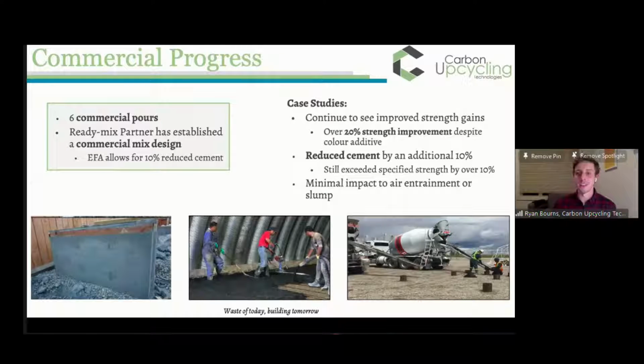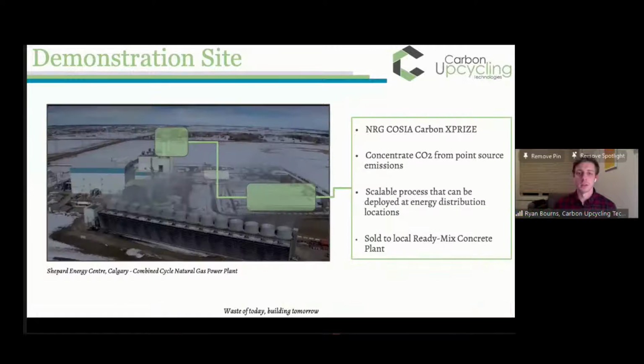As Matthew mentioned, there's a very thin margin that you can work within, and 40% is way above that. So what we really want to show is that because of that strength improvement, we can really reduce the cement that would be associated with it. This is something we're still working on and optimizing with our concrete partners. But what we've shown here is that we can keep all of the necessary considerations for concrete the same, whether it's air entrainment or workability, but with improved strength and reduced cement. And this is something we've shown in these commercial trials.